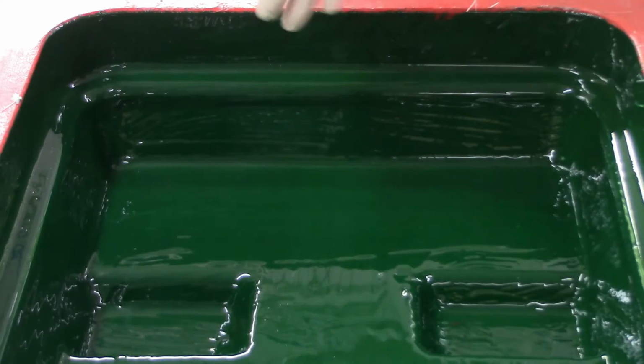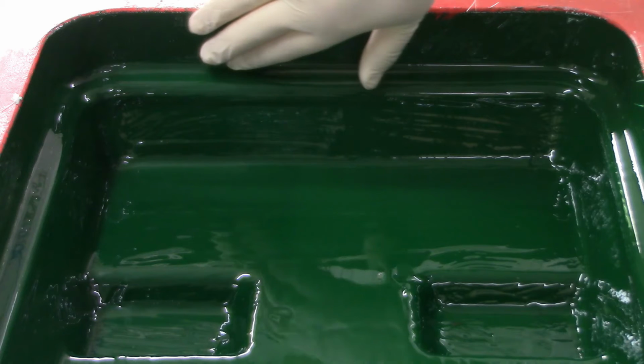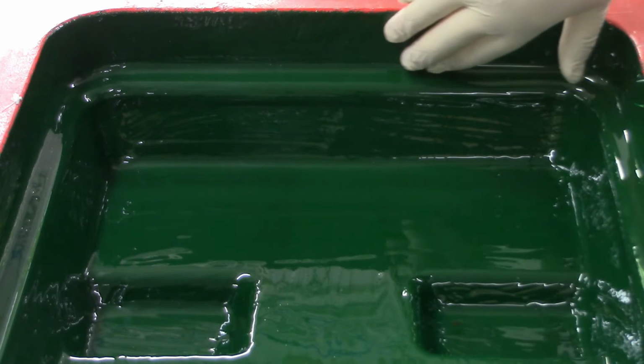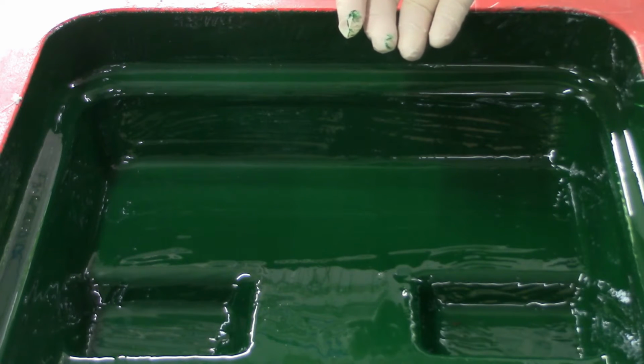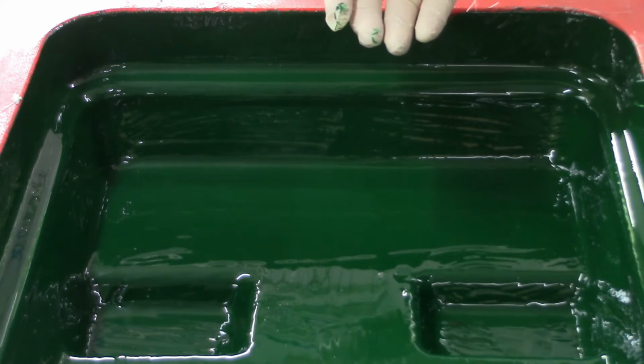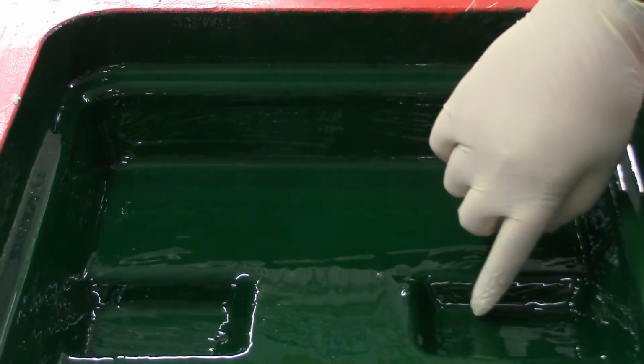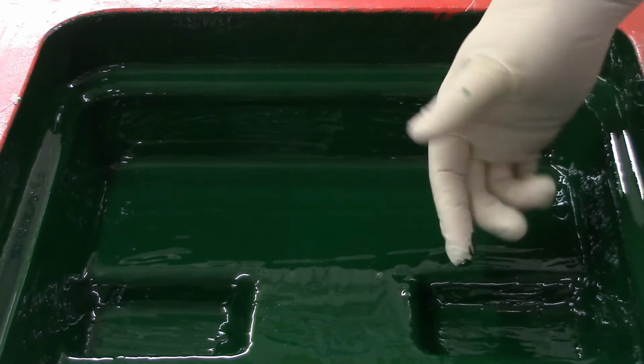Your Gelcoat should feel tacky to the touch when cured, but when dragging your fingers over the surface, there should be no colour on your fingertips. Check the deep areas of the mould too. These areas take longer to cure.